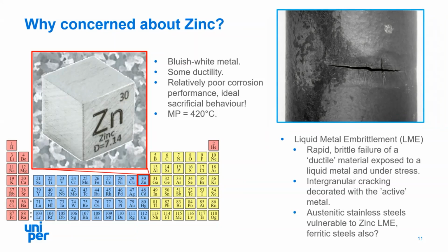What's shown here is exceptional. This is an example from the mid-1970s of a stainless steel reheater tube to which a thermocouple was attached using a galvanized clip. Operating at temperatures up towards 600 degrees centigrade caused the zinc to fuse into the tube wall and result in failure as shown here. What we do recognise is that austenitic stainless steels are vulnerable to zinc liquid metal embrittlement. The question is, are ferritic steels also, with respect to the grade 91 that we were seeing?